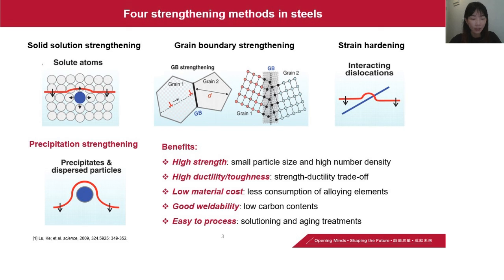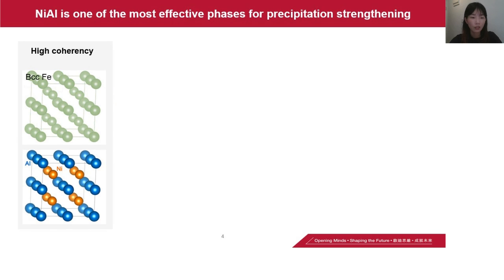Generally speaking, precipitates with a small particle size and high number density have allowed the development of advanced steels with high strength, high ductility, good weldability, and low cost. And this method is very easy to process because the treatment process is very simple. Among various potential precipitates used for precipitation strengthening, nickel-aluminum is one of the most effective phases.